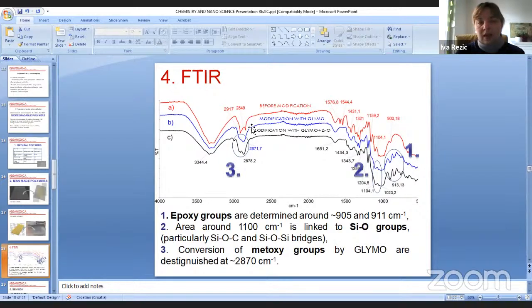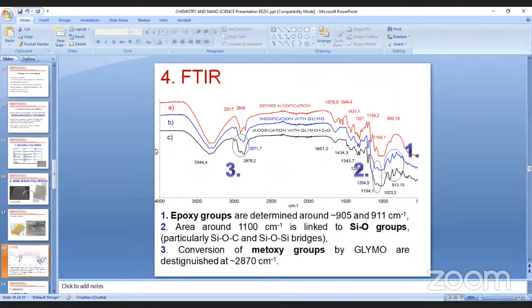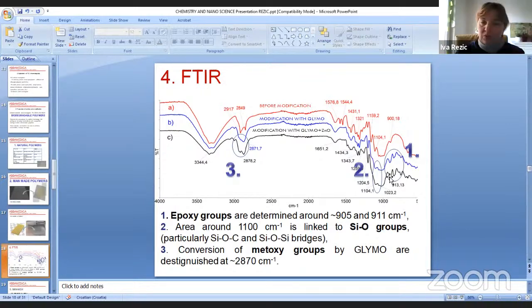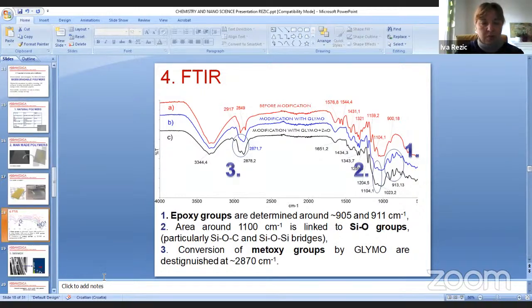So in this picture, you have the red line, which is actually our sample before modification. And then we have blue and black lines after modification. And you can really see that around 900 centimeters, we have epoxy groups which have occurred. Around 1,100 centimeters, we have groups with silica. And here around 2,870 centimeters, we have conversion of methoxy groups by GLYMO. So this is the result of this chemical modification by sol-gel process methodology, and this is actually how we can prove that we have a really stable coating on our polymer.